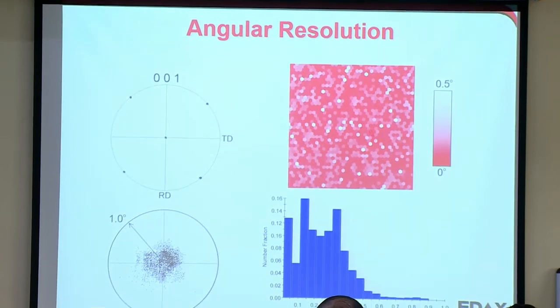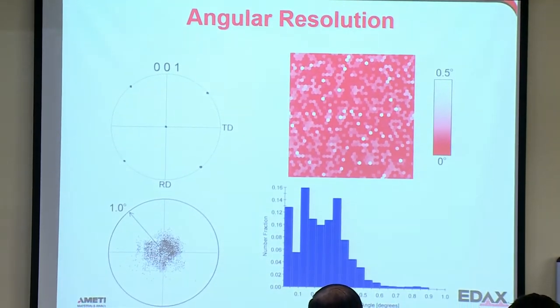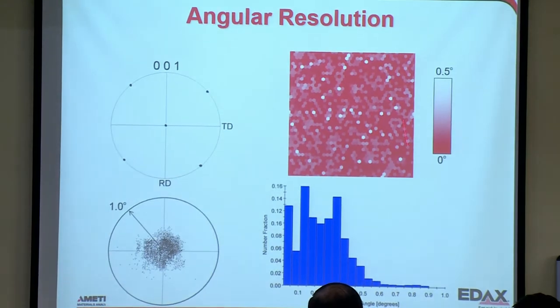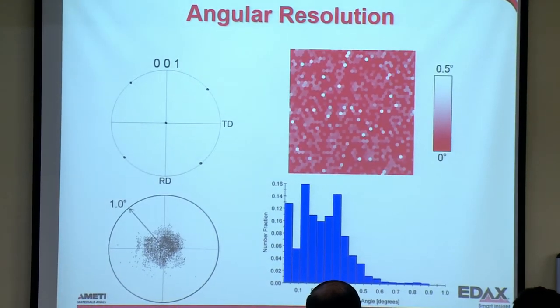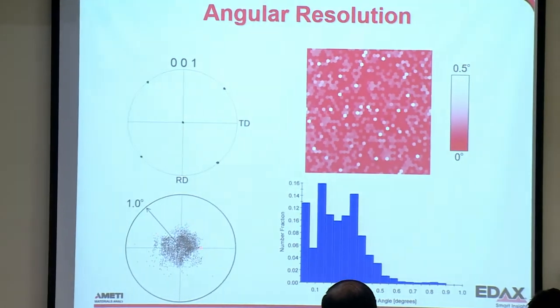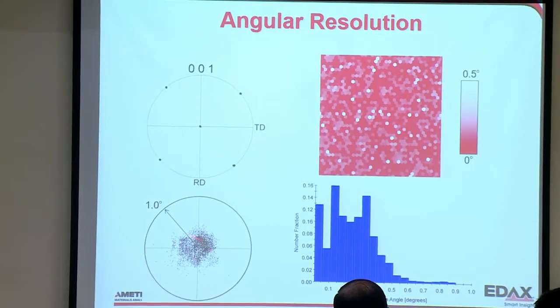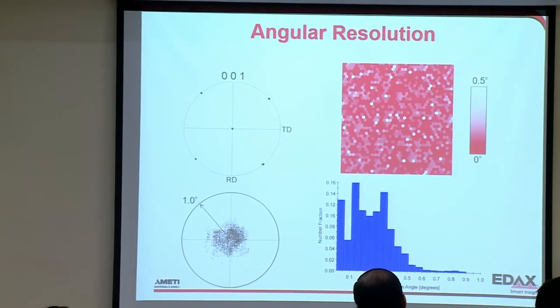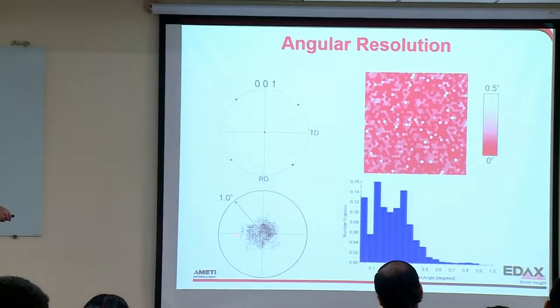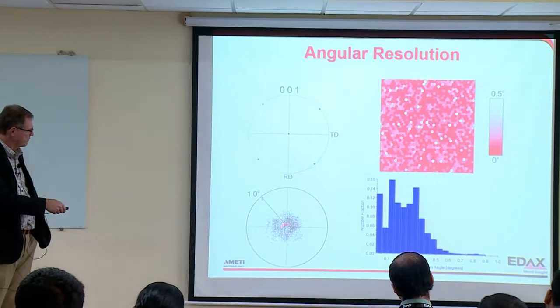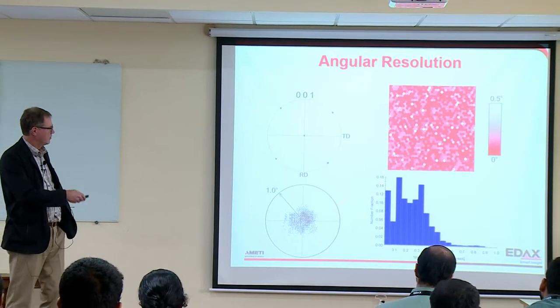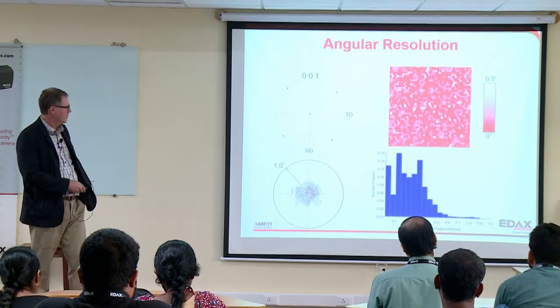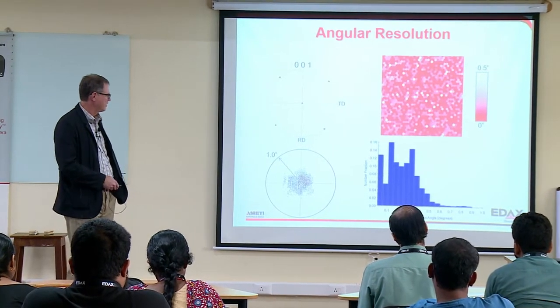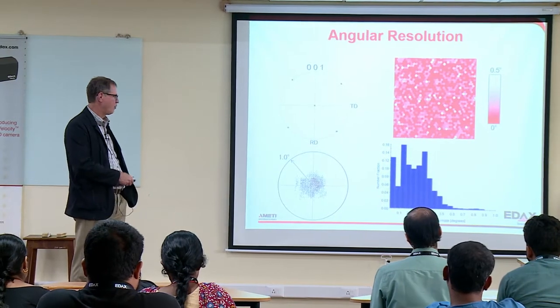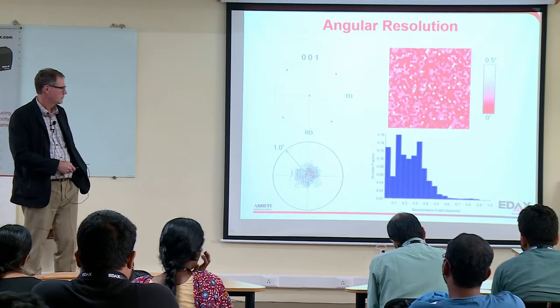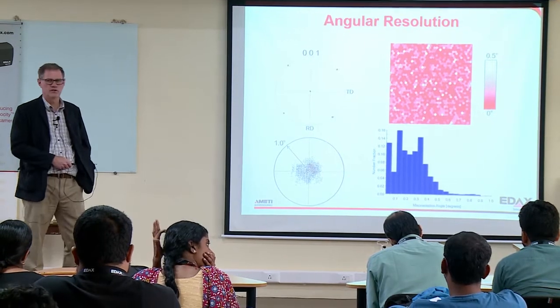The angular resolution, there's a couple different ways to measure this, but this is from a single crystal, a millimeter by millimeter scan. If you look at the pole figure, it looks really good, but if you zoom in, you can see a lot of these points are clustered within about half a degree away from the center. Well, this is a half degree, so really about 0.25 degrees away from the center. And so this is the distribution here. So the angular resolution, there's different ways you can describe it, but typically we can get down to about 0.1 if we're really, really careful. But I would say 0.2 to 0.3 is probably more typical.